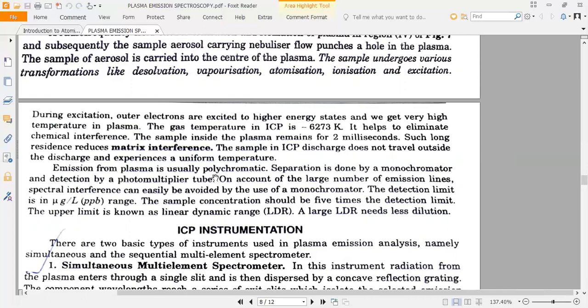Emission from plasma is usually polychromatic. Separation is done by a monochromator and detection by a photomultiplier tube. On account of the large number of emission lines, spectral interference can easily be avoided by use of a monochromator. The detection limit is in the microgram per liter range. The sample concentration should be 5 times the detection limit. The upper limit is known as linear dynamic range. A large LDR needs less dilution.